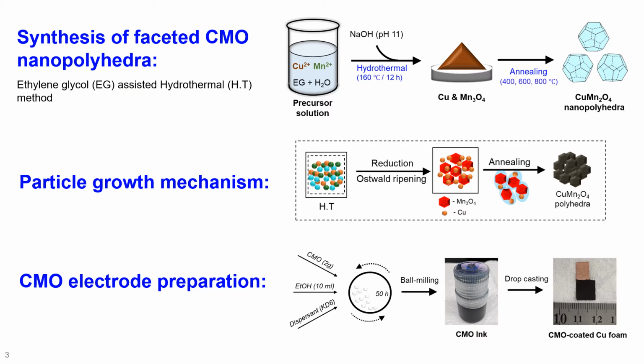Here, the particle growth mechanism of CMO. After taking the powder from the hydrothermal treatment, it is a mixture of Cu and Mn3O4. We have confirmed it via XRD. I will discuss it later. So here is the particle growth mechanism. Ethylene glycol played an important role as a reducing agent to produce copper, and via the Ostwald ripening process, Mn3O4 nanopolyhedra have been formed. Then during the post-annealing process, these two, that is copper and Mn3O4, undergo a solid state reaction to finally produce CuMn2O4 nanopolyhedra.